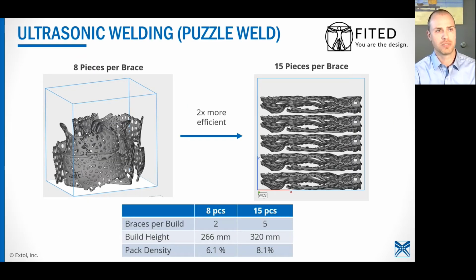So if we look again at this, when we first got this, it was about 8 pieces per brace. And with the idea of minimizing assembly, the intent was to use glue, but it did not optimize the build area, and a lot of the cost is driven by how much of that build area and build volume we are optimizing. So through breaking it down into 15 more pieces, we added, yes, incrementally more assembly, but drastically improved the efficiency of our build packing. So basically we cut the cost of the printing portion of this in half by doubling the efficiency of the print.